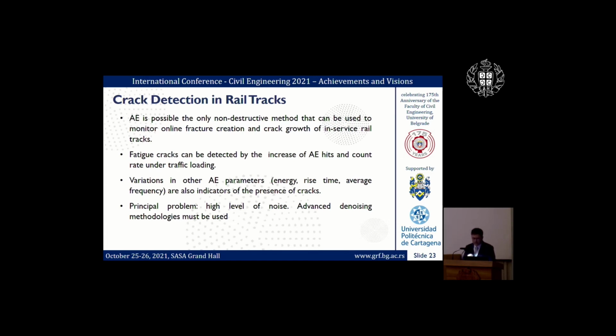It has been found that fatigue cracks can be detected by the increase of acoustic emission hits and the count rate under traffic loading, and by the variance in other parameters like energy, rise time, average frequency, that can also be indicators of the presence of cracks.